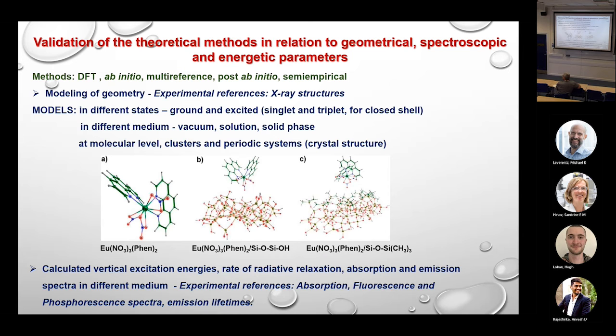going to different media: vacuum, solution, solid state, or modeling the molecule as the active material, or when modeling the absorption of this photoactive unit into the silicate matrix. In this case, we use a cluster approach. So our aim is to approach the experiment. And we test and validate our methods with reference to the experimental X-ray structure. This is why it's very important to have this information from experimentalists.